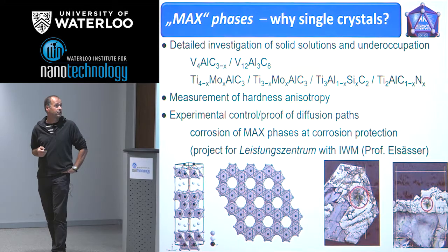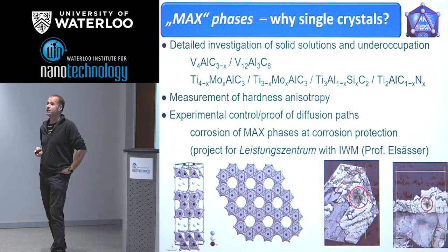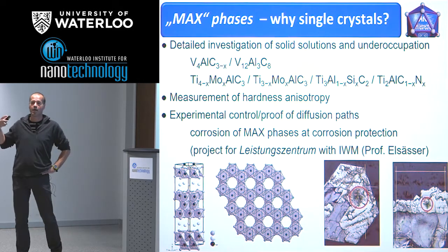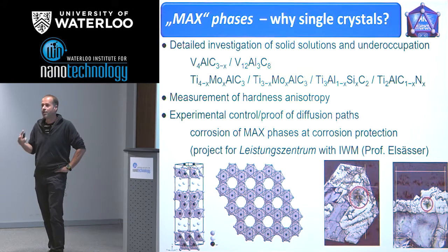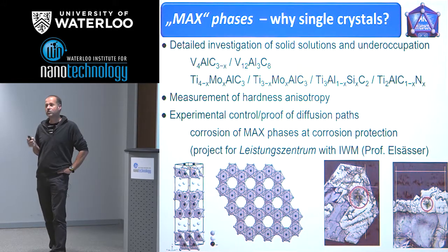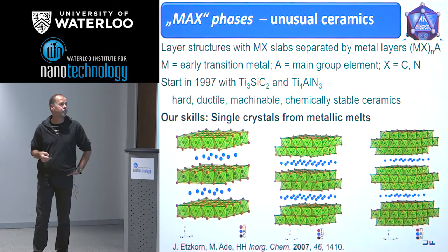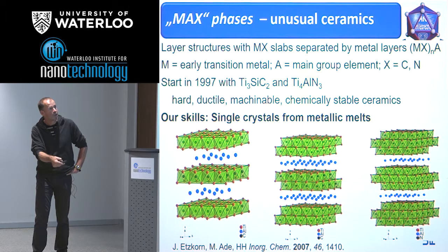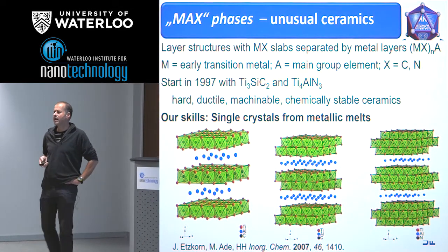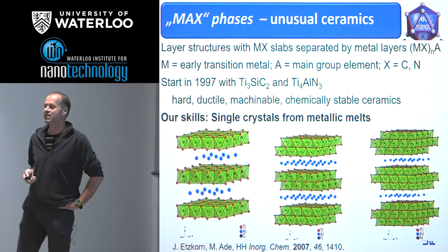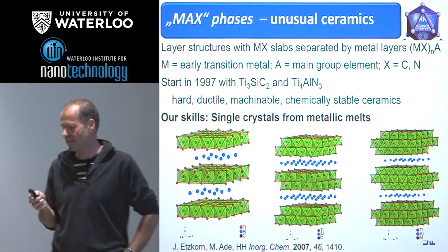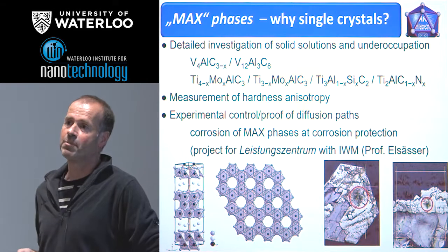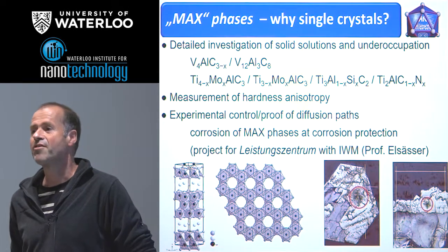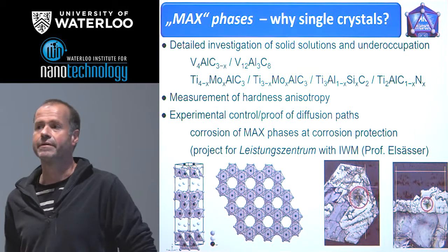Another point, why single crystals? We can measure micro hardness for the single crystals. If you try to model the physical properties, we know that we have strongly anisotropic behavior. That means the hardness and the deformation processes are very different between the different directions. And it's quite easy to calculate it, but it is very difficult to measure it. And so you need a single crystal to measure the anisotropic properties of the material.